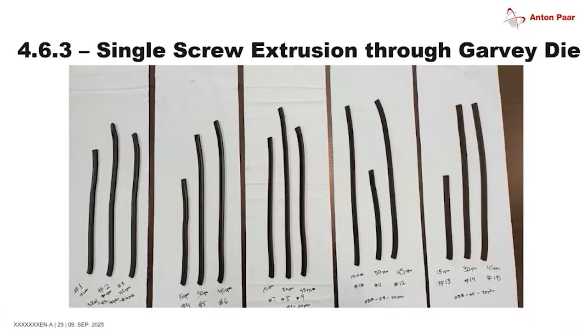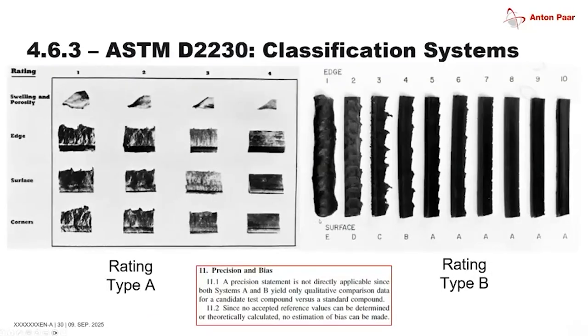So bear with me, you guys are in for a treat. You're going to see a lot of black extruded samples. But this is the point of this exercise, that you understand there are some downfalls to this method, and we try to offer some solution of how you can quantify the qualitative test. So again, our different 70 PHR samples of the 3 different carbon blacks. This is exactly what I was talking about. I sit in the D11 committee, and we're still having a standard where this is literally the reference that is printed and probably copied a million times. And in our modern day and age, there's most definitely a way to improve that.